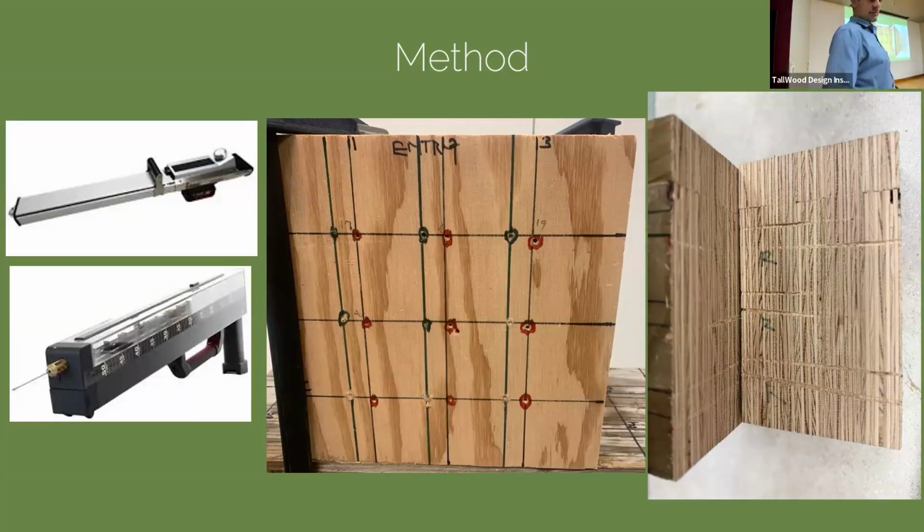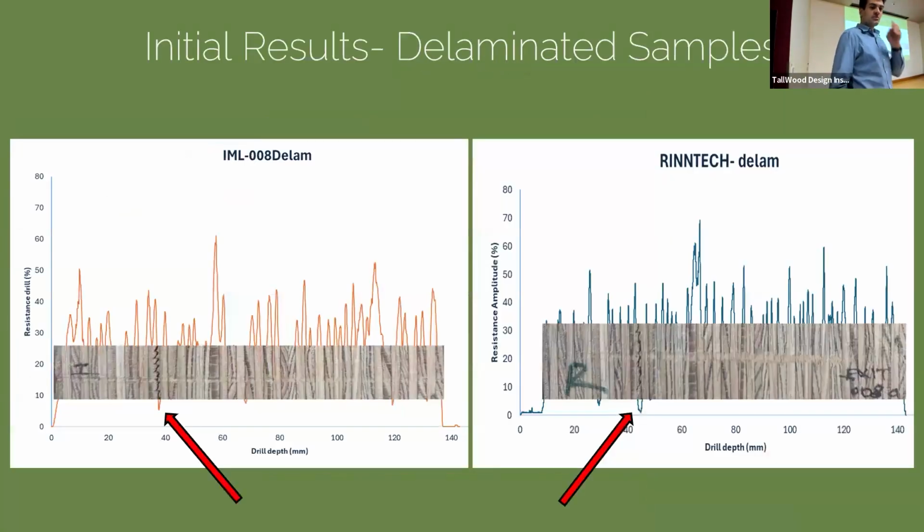And so the idea is, particularly with the decayed samples, you're going to have points of fungal entry. And so you're going to have more decayed wood over here. And as the fungus advances into the middle, it's less decayed because the hyphae have been in contact with that wood for a shorter amount of time. And so ideally what we'll be able to do is identify what kind of resolution we have with this equipment to identify decay.